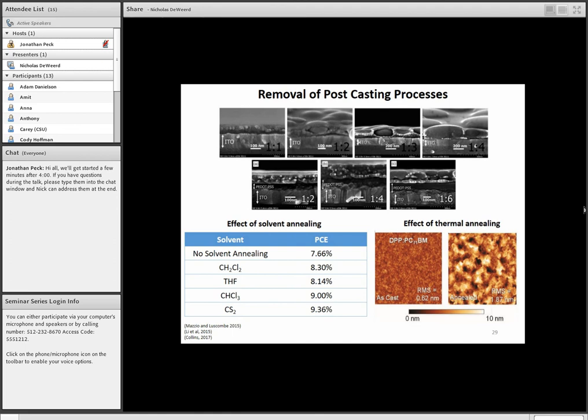But you're seeing a very large difference in terms of the morphology by changing variables. In this case, we're changing the fullerene to donor ratio, or we're changing the solvent that they were spin casted from. It doesn't really matter what they were, but the point is that you can control it without having to do these secondary processes. So as I said, on the research scale, these secondary processes are fine. They're incredibly valuable to researchers, but on the industrial scale, you can envision a much more simple production line by not having to utilize these different technologies, the thermal annealing or the solvent annealing processes.